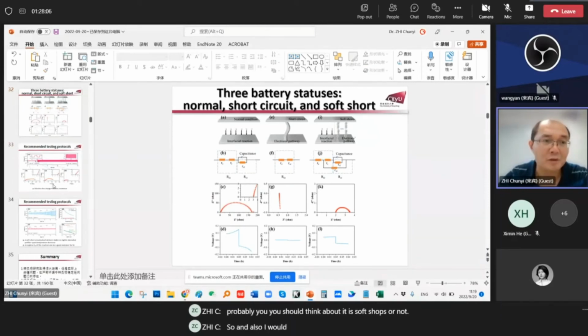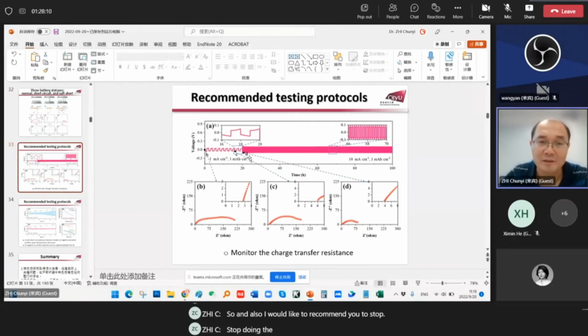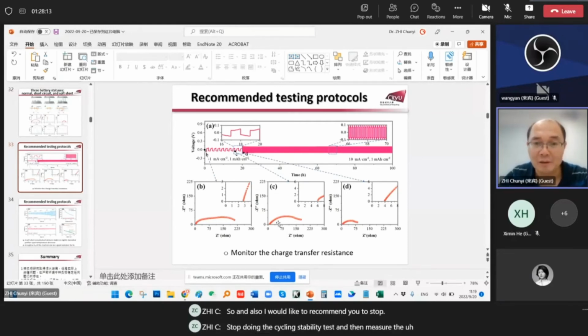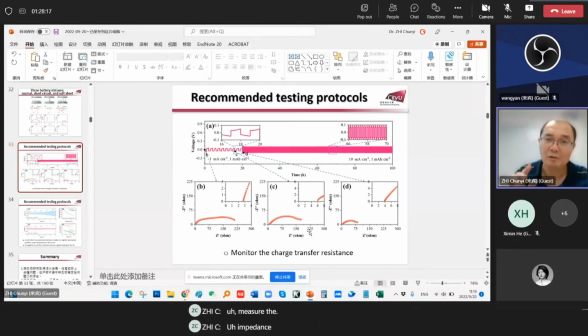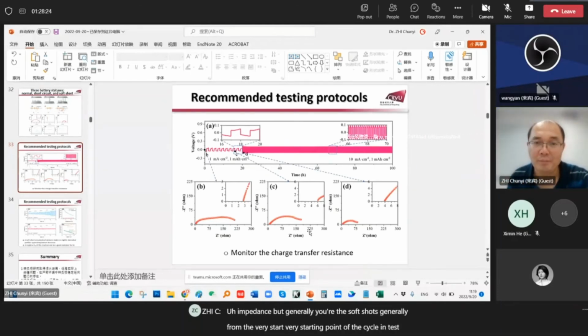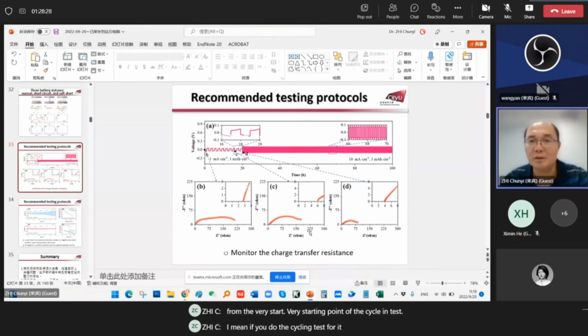I would also recommend that you stop the cycling stability test and then measure the impedance. But generally, soft shorts arise from the very starting point of the cycling test. If you do a cycling test of, for example, 10,000 cycles, you can do the impedance test at the beginning, and at 100 cycles, 200 cycles. If it's stable, it will generally be fine. Soft shorts generally start suddenly when you apply a high current density. And if it becomes stable, there will be no soft shorts for a long time. The beginning is the dangerous period.